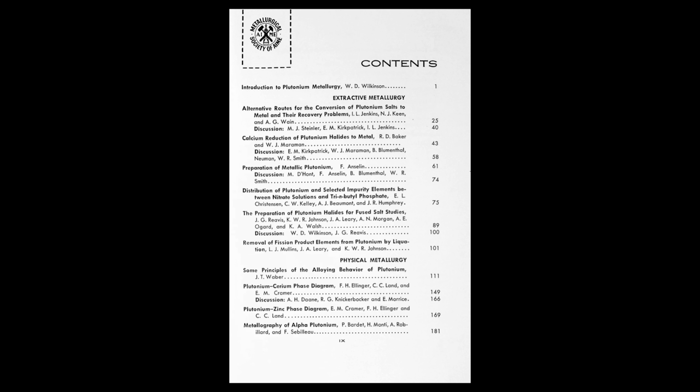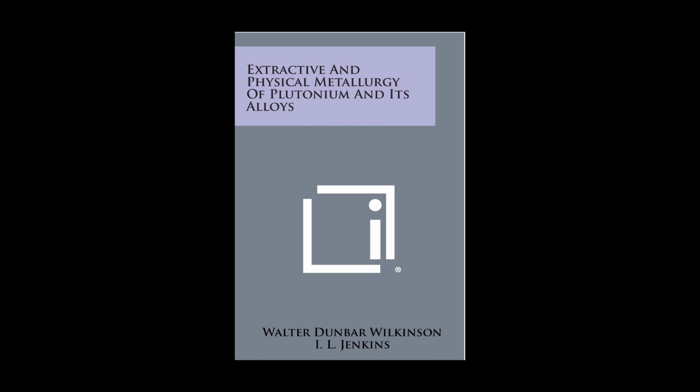Okay, cool. Let's look at one then. The plutonium-cerium phase diagram, figure 1 in that section. What jumps out from that map? One of the really significant things in the Pu-Ce system is the extensive solid solubility of cerium in delta plutonium. Delta plutonium, that's one of the 6 forms, right? Yep, one of the higher temperature solid forms. An extensive solid solubility means you can dissolve a whole lot of cerium atoms into the crystal structure of delta plutonium, and it still stays as one single uniform solid phase over quite a wide range of temperatures and compositions too.